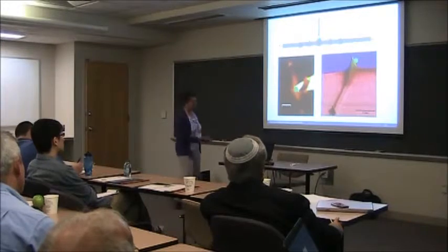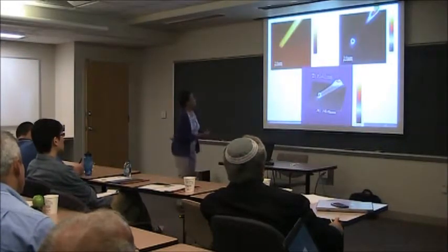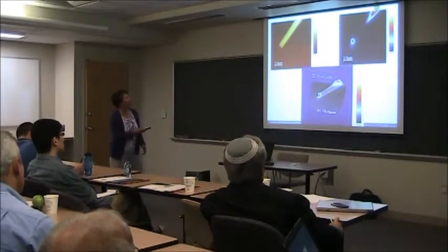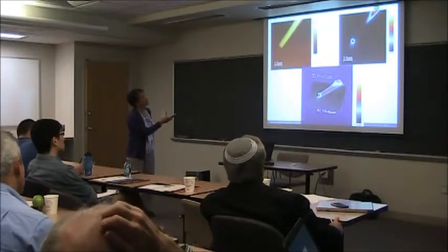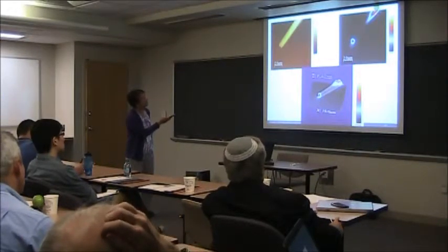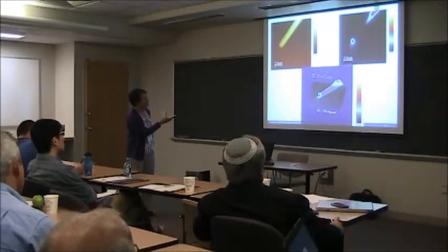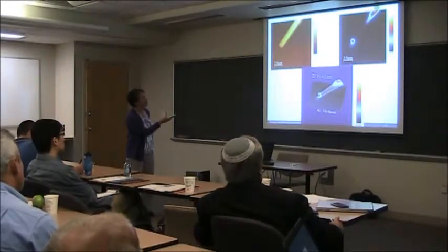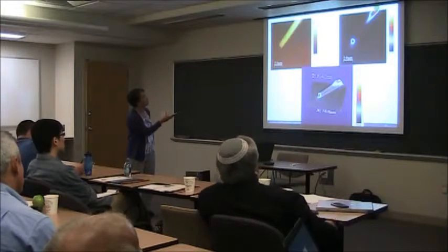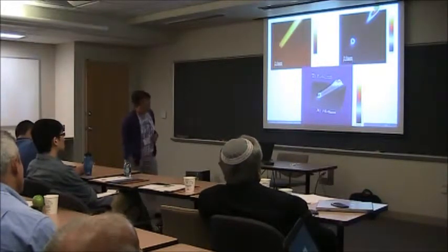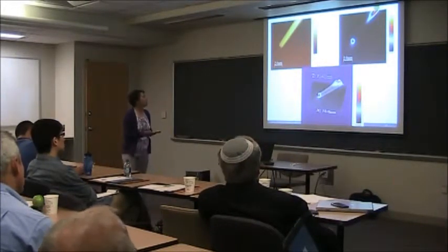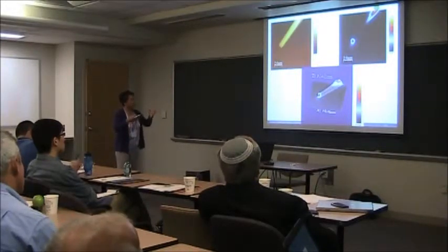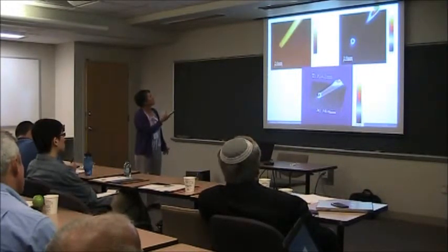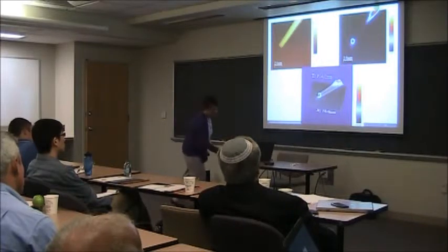All right, so those are the pictures that we kind of see. And here's another example. So again, the electron beam is up here. This is the NSOM image. Again, basically similar to what you saw before. There's the wave guiding, there's what we believe to be the carrier diffusion. Our AFM images are not great. They've gotten better over time than this one, but we're convoluting these two things, so we're not trying to get high-resolution AFM, although we should do better. But that at least gives us the axis for which to compare, and then we can make these pictures.